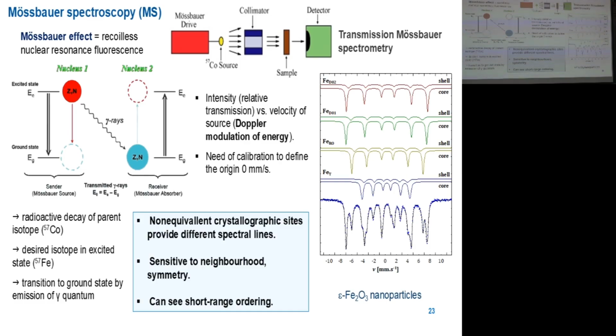And importantly, the spectrum contains information about the oxidation state, and also about the neighborhood of these iron atoms. So you can use it, for example, to determine the quantity of iron in the tetrahedral and octahedral sites of the spinel structure we mentioned earlier. And you can determine at the same time the amount of iron 2+ and iron 3+.